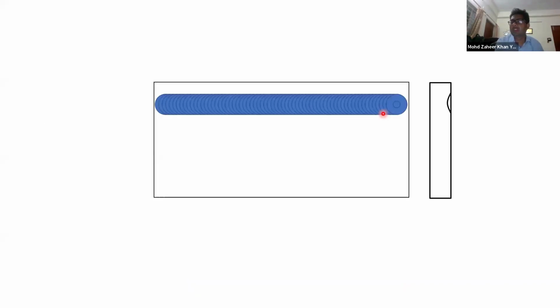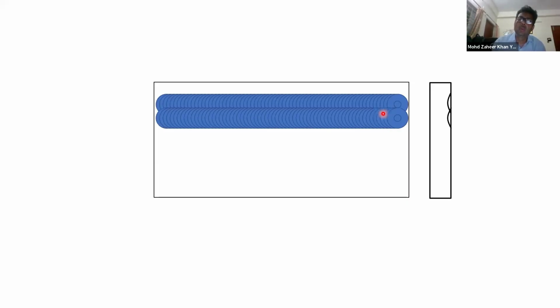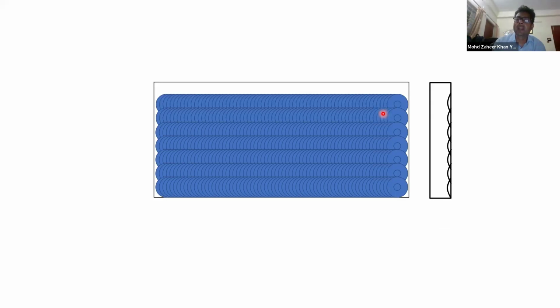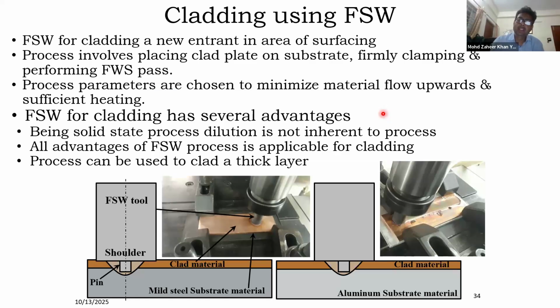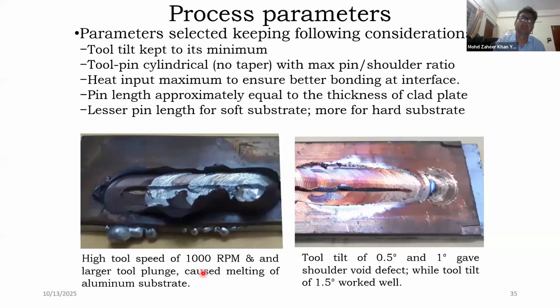So this is how several passes are made. Let us say there is a substrate, and on top of it a clad plate that has been pushed. So overlapping passes are made like this, and the entire plate can thus be covered. And if required, then a little bit of machining can also be carried out. So this is the first experiment that we have carried out. In the first experiment, we have deposited a layer of copper on the aluminum substrate. And in the other set of experiments, we have deposited a layer of copper on top of a mild steel substrate using multiple friction stir welding passes.